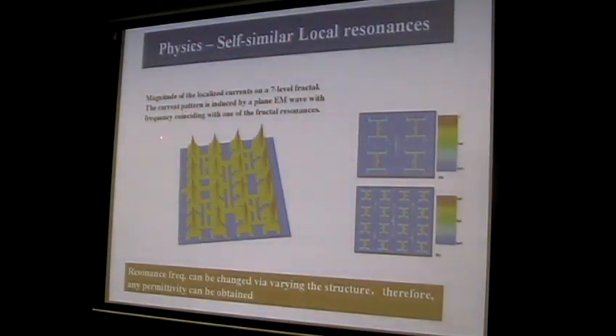So what's the physics? We found the physics is governed by a series of self-similar local resonances. This is a typical picture showing the distribution of the current. You can find that for a particular resonance frequency, the EM wave will excite the current along a particular line, and then the current will flow to the ends of the structure. For another frequency, the excitation will excite another line, and then the resonance frequency is different from the lower frequency one. This is the lower frequency, and this is the higher frequency resonance.